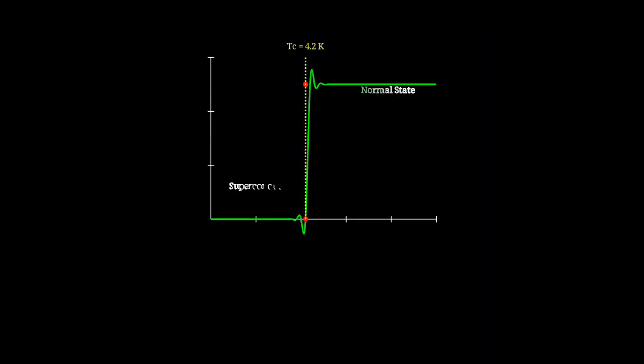This is the remarkable result. Above 4.2 Kelvin, the resistance is constant at about 0.25 ohms. But at exactly 4.2 Kelvin, the resistance drops discontinuously to zero. Not just very small, but actually zero within measurement precision. The transition is extraordinarily sharp. The resistance drops from its normal value to zero over a temperature range of less than 0.01 Kelvin. This is not a gradual change, it's essentially a discontinuous jump.